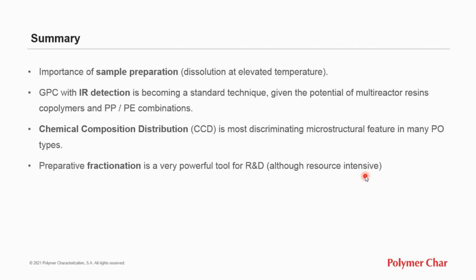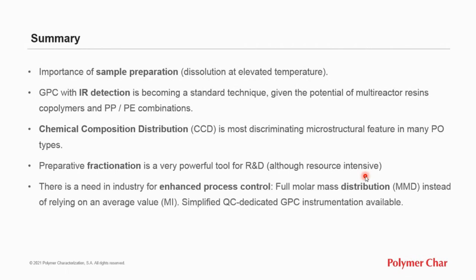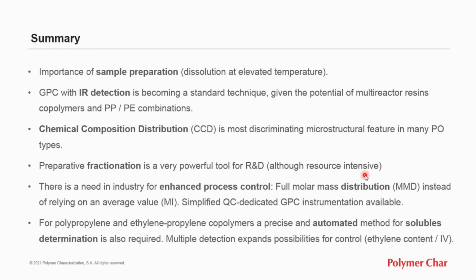Preparative fractionation is also a very powerful tool for R&D, although it's a resource-intensive technique. And finally, I also emphasize that there is a need in the industry for enhanced process control based on the full molar mass distribution, MMD, instead of relying on average values like melt index. And for that application, we developed the simplified QC-dedicated GPC, which is available. For polypropylene and ethylene propylene copolymers, a precise and automated method for solubles determination is also required. Multiple detection expands the possibilities for control, adding the ethylene content and the intrinsic viscosity of the fractions and the total.